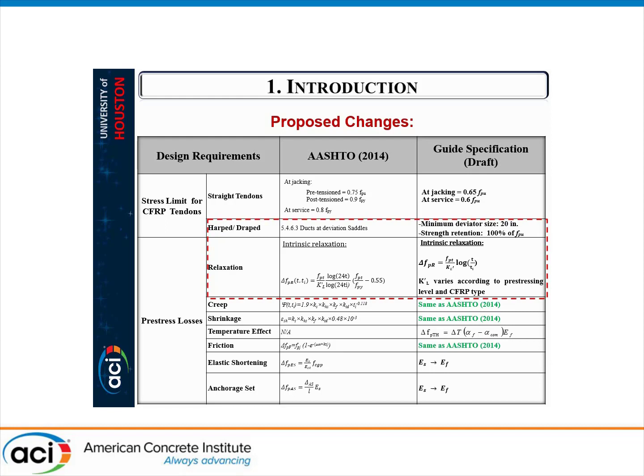For instance, regarding stress limit of CFRP tendon, for a straight tendon, we have lower jacking stress limits. As you know, because of creep rupture restrictions in CFRP material and due to the brittleness of this material, we have to maintain enough reserve tensile capacity. So we have to lower the jacking stress limits. And also regarding harping and deviators, we have some restrictions on the harping angles and deviator sizes that need to be included in our guidelines. And also we look into all the prestressing losses, including instantaneous and long-term losses, such as relaxation, concrete creep and shrinkage, temperature effect, friction losses, elastic shortening, and anchorage sets. So in this presentation, I'm only focusing on two items, harp and drape and relaxation tests.